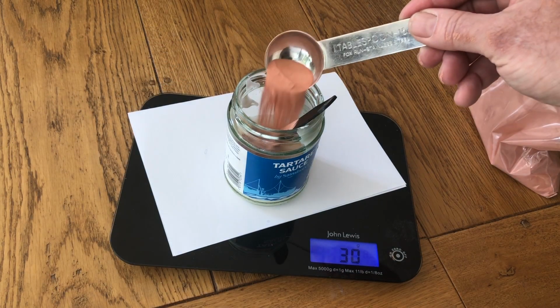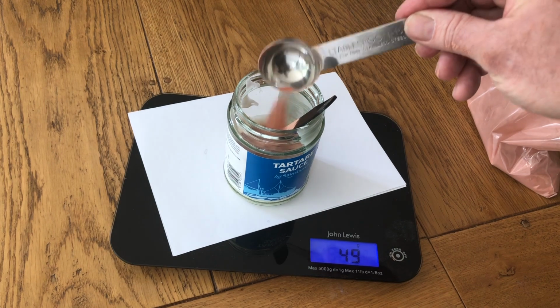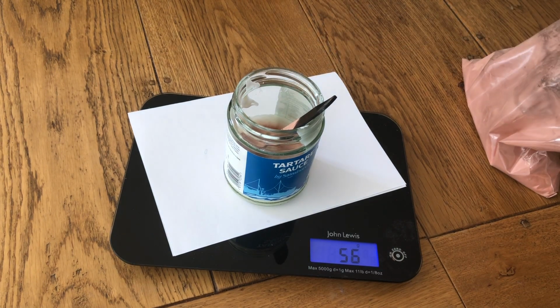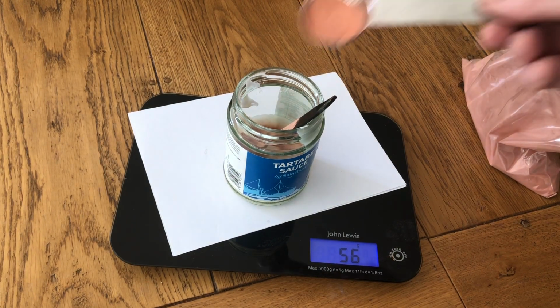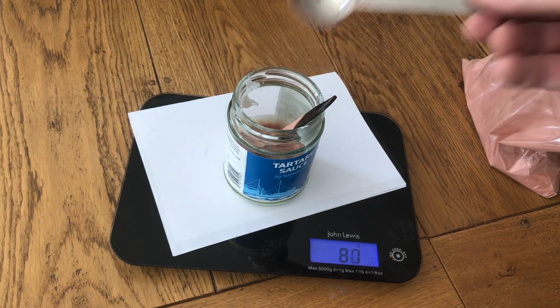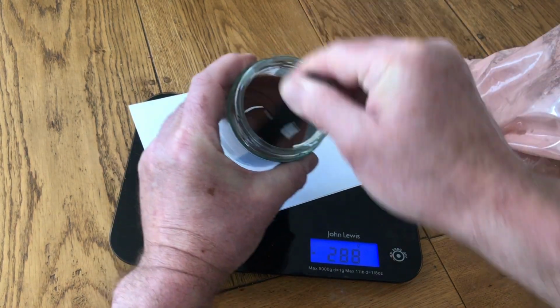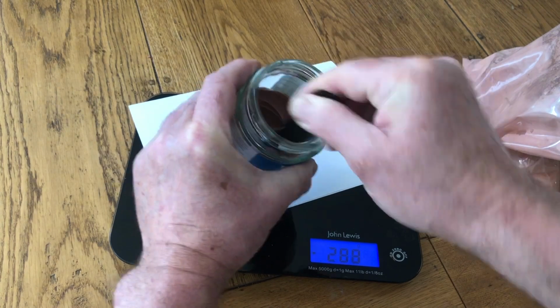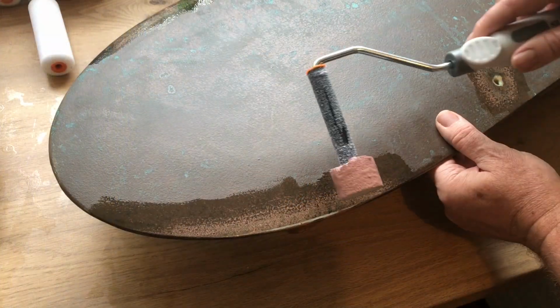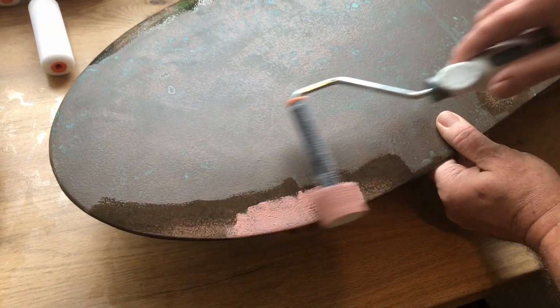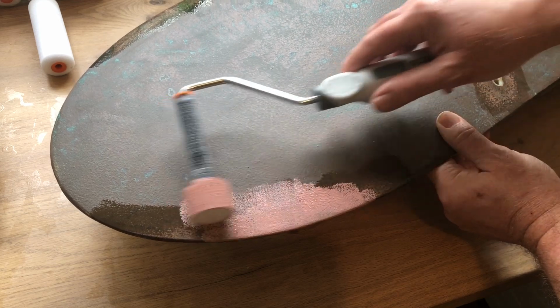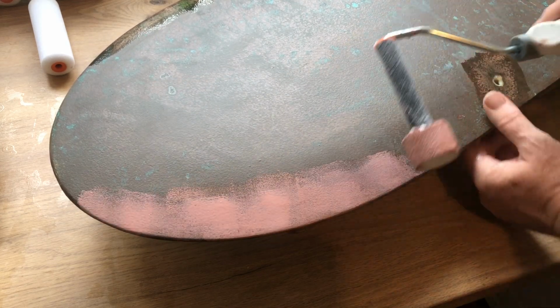When mixing batches for the second and subsequent coats, the copper powder should be added. Mix 1 part resin and 1 part hardener together. Then add 4 parts copper powder. Mix thoroughly. Coppercoat should be applied directly after mixing and stirred regularly throughout the application process to prevent the copper from settling at the bottom of your container.